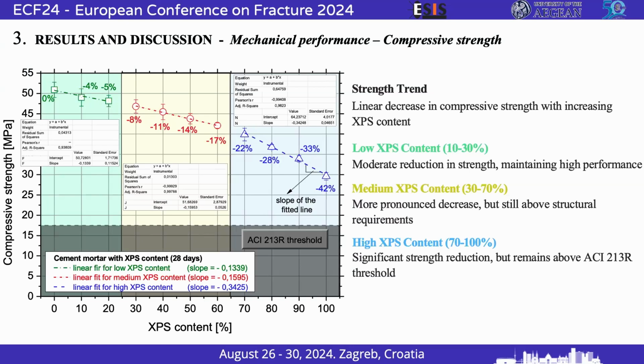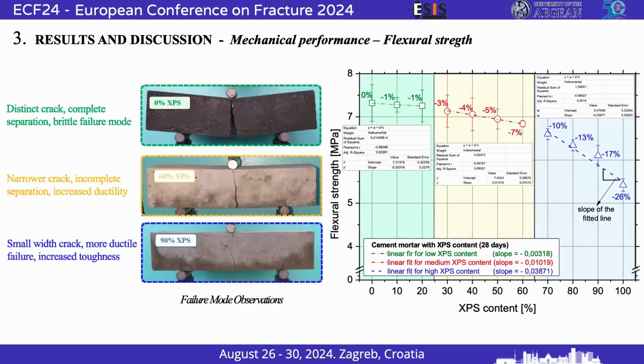Also, we have seen that at low XPS content, from 0 up to 30%, there is a slight decrease in the compressive strength, like 5%, which is minimal. Then at medium XPS content, from 30 to 70%, there is a more pronounced decrease. And the significant reduction in the compressive strength happens at very high contents, from 70 up to 100% XPS. Looking at the flexural strength, we can see the same trend.